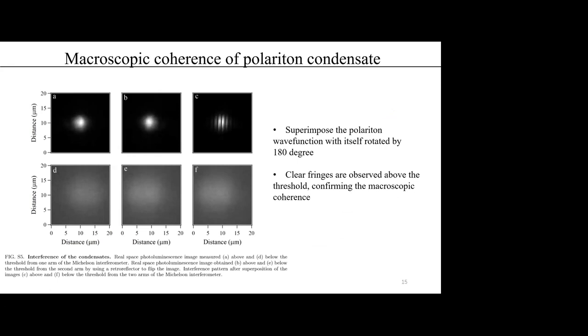Polariton condensation should be accompanied by the build-up of macroscopic coherence. We measure the macroscopic coherence of the polariton condensate by building an interferometer, where one arm is rotated by 180 degrees. The interference fringes are clearly observed above threshold, which confirms that the macroscopic coherence has been built up above threshold across the polariton condensate.